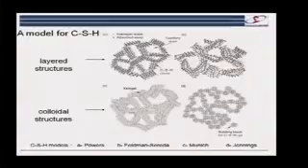In the last few decades, there's been an awful lot of work with scattering experiments, which have indicated that there's a characteristic size of this intrinsic porosity, maybe in the region of 4 to 5 nanometers. So this was a starting point for various models. And then over the years, people have put forward lots of different models for this CSH structure.